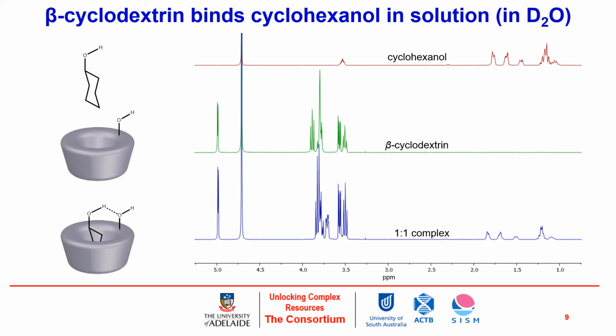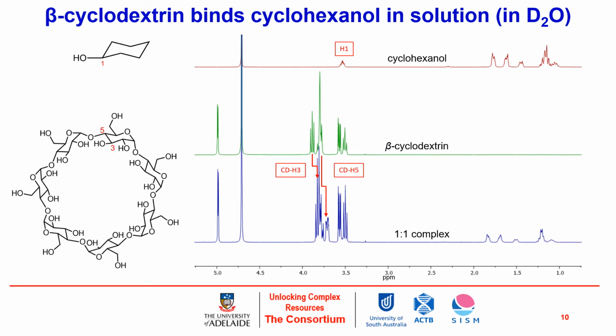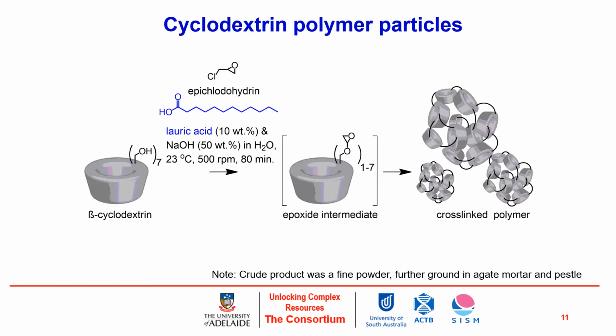So without going too in depth into the ins and outs of NMR, what this means is that I can see the key interactions between cyclohexanol, in this instance, and beta-cyclodextrin, particularly the 3 and 5 protons of these sugar residues, which interact and shift in their environment within the magnetic field, confirming that this has formed a host-guest complex.